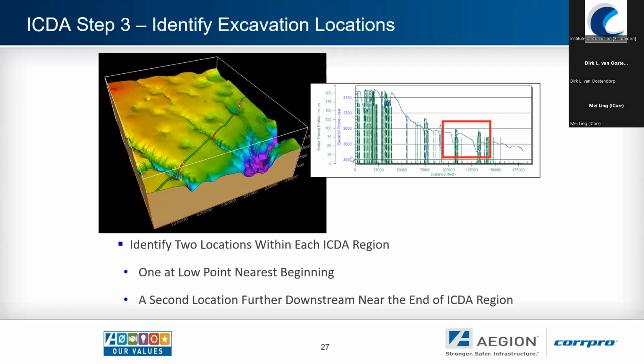In the one case in particular, I think it was the second location downstream, what we found is that with the modeling, when we did the dynamic modeling, there was almost a reflux situation that was taking place there, where the water would actually rise up the uphill slope, but then start to slide back down because there wasn't enough momentum in the gas stream to push it all the way. So there was almost a reflux at that particular location. And that was an area of interest to us for further inspection using NDT.